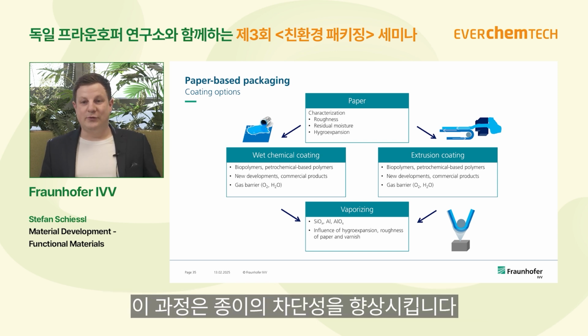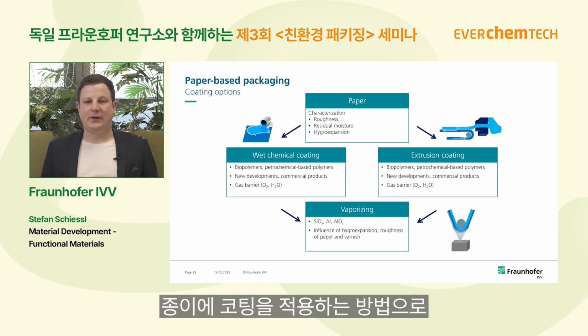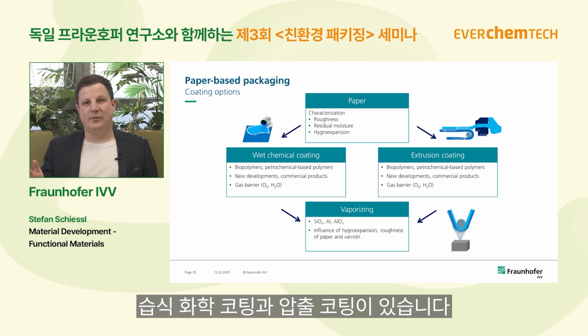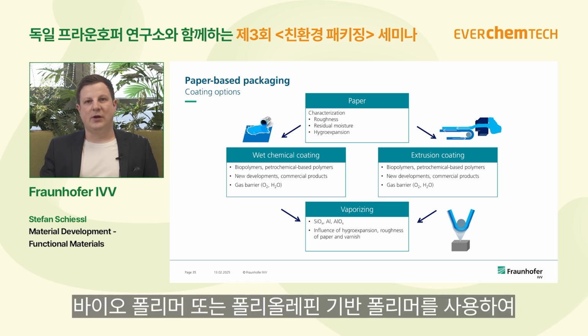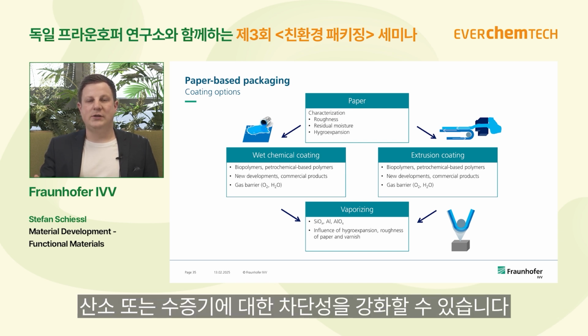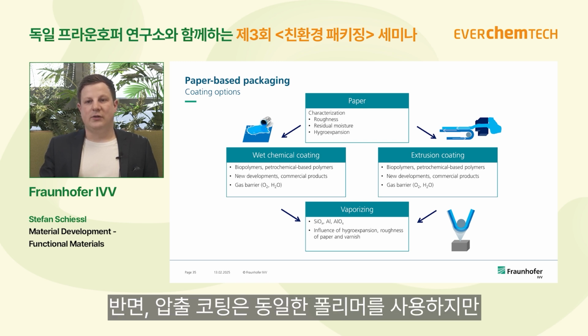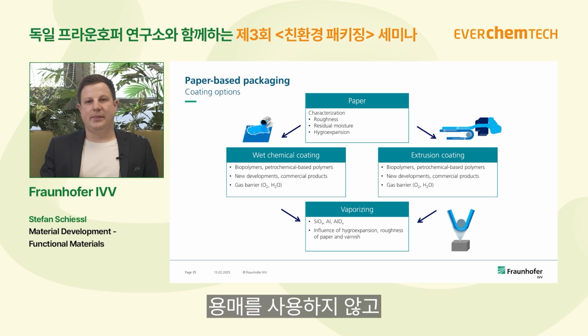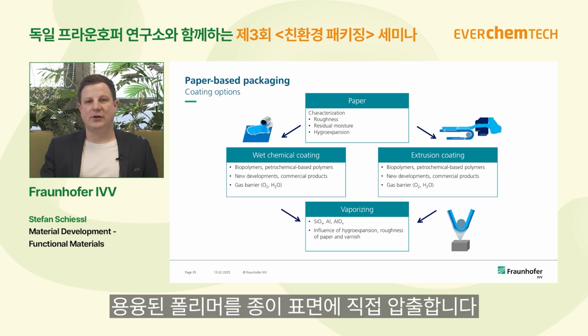That means to improve the barriers of the paper, there is the option to do a coating on paper, and this can be done either by wet chemical coating or by extrusion coating. The wet chemical coating can be done with biopolymers or also with polyolefin-based polymers to increase the barrier against oxygen or water vapor. The extrusion coating, on the other side, can do with the same polymers, but the difference is there is no solvent involved, so there is a direct extrusion of the molten polymer on the paper surface.